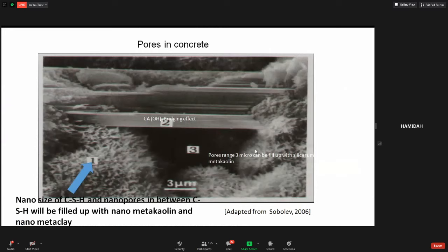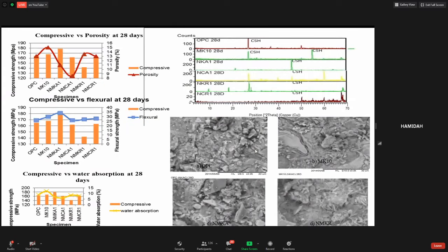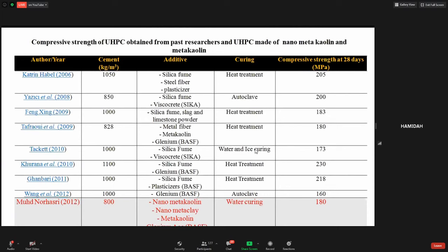The function of nanometaclay or nanometakaolin is obviously to fill up pores in nano size in concrete. The results show that nanometaclay has flaky and granular morphology. It shows that 1% nanometakaolin is enough to boost the compressive and flexural strength to the maximum level of the UHPC prepared. Interestingly, it is noted that the compressive strength achieved is equal to those made of higher cement content and cured under heat treatment when nanometaclay or metakaolin is included in UHPC.